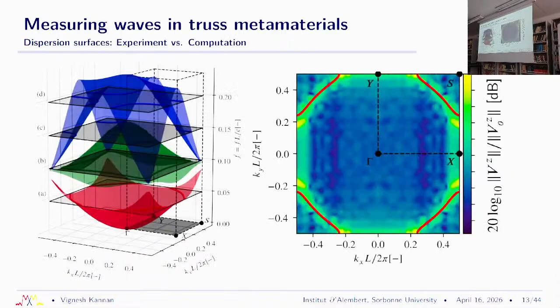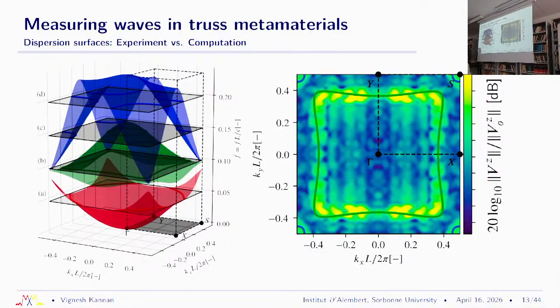So we went back to Bastian's computations, right? And we said, let's look at whether our experiment is able to capture the full dispersion, and for how many modes you can actually capture this dispersion. So what you see here is the same picture that you saw before, but the background color intensity is from experimental data. So we take our position as a function of x, y, and time, or a displacement as a function of x, y, and time, and we basically do a three-dimensional Fourier transform of that data. And what you see here is one data set.